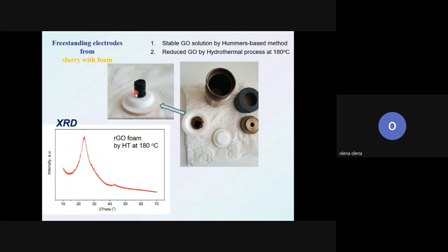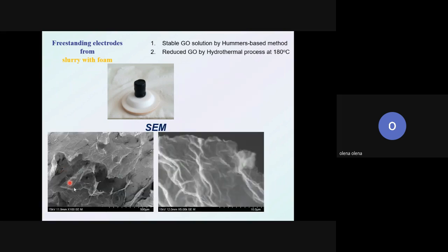It's dried, and we study by XRD. Yes, we have strong peaks at about 24 degrees, and not about 10 like for graphene oxide. So we have reduced graphene oxide. We study by SEM. You see, this is 500 micrometers and 10 micrometers. In comparison with the previous, it looks thinner and much better.